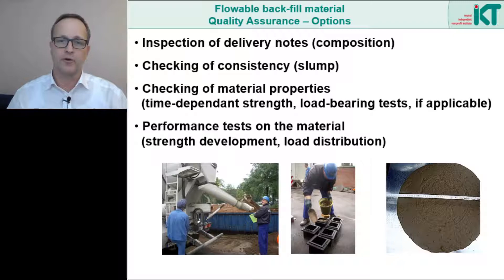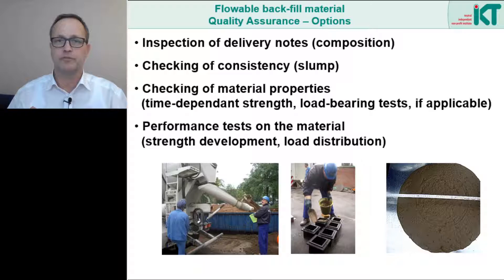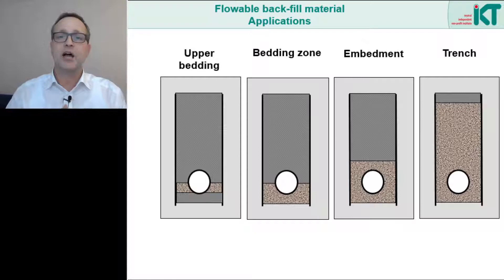Overall, quality assurance on the construction site plays a very important role. Delivery notes must be checked and sufficient sample material should be taken directly from the truck mixer to carry out appropriate tests. The tests include, for example, the consistency of the material and testing the strength over time using cube samples. The results can then be compared with the characteristic values from former performance tests.